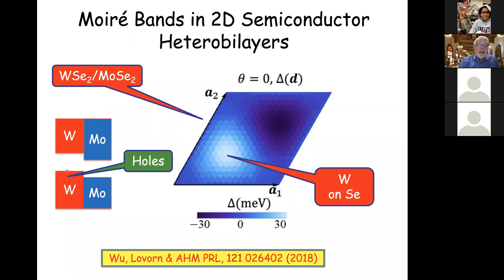And if you have a Moiré pattern like the one I showed you, then the spatial coordination between the tungsten layer and the molybdenum layer will vary slowly in space. What is shown on the right-hand side here is an estimate that we did several years ago of how the energy of a hole at the top of the valence band in tungsten varies as you move the molybdenum layer underneath by a certain amount. And what you find is that the top of the valence band, which are electrons on the cation tungsten sites in this material, they're localized on the metal site in this material.